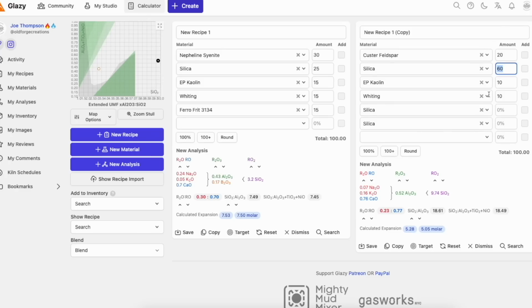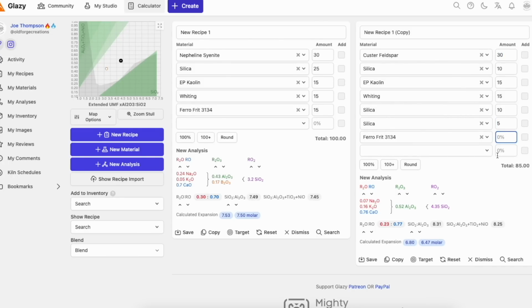We're looking at a perfectly normal recipe that has 25% silica. We could just have 10% quartz, 10% flint, 5% silica. Doesn't matter which we do because they're all identical. Now we're at a sensible sort of level. We only total 65%, so we'd have to bring the others up to sensible levels. There, that's fine. So we got slightly different because we're using Custer instead of Nepheline, but fine. We've used 3 sources of silica, and what we've done is we've decreased the amount so that it makes sense.